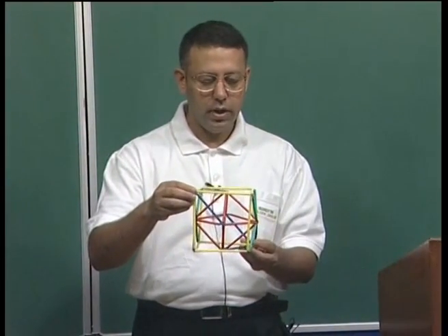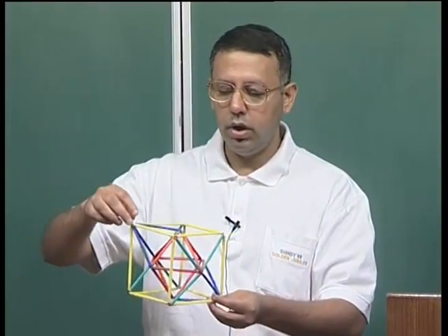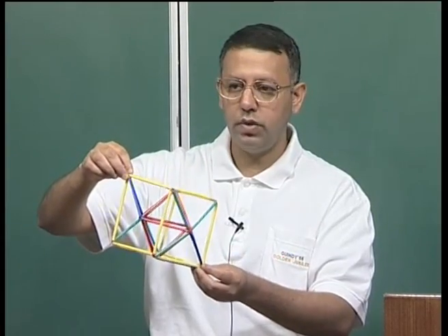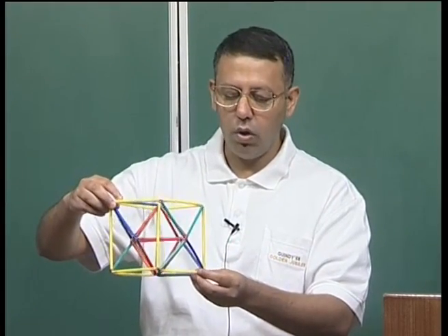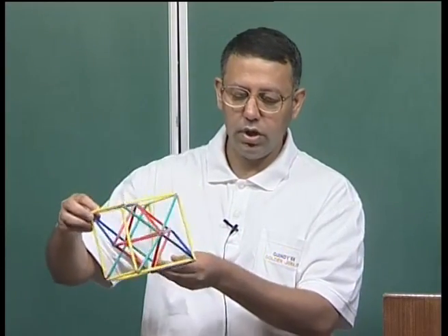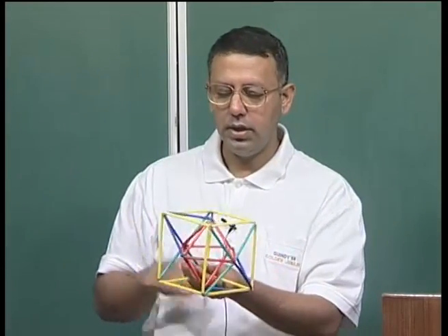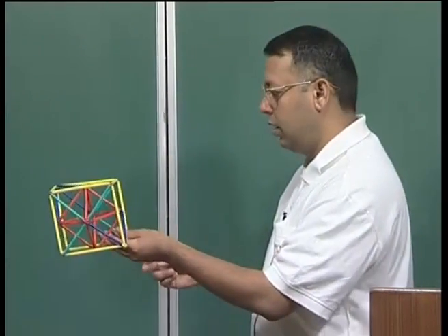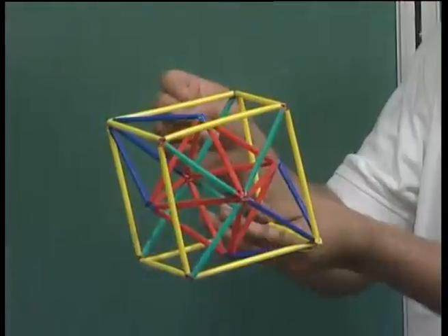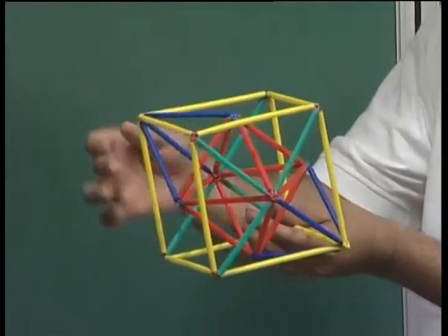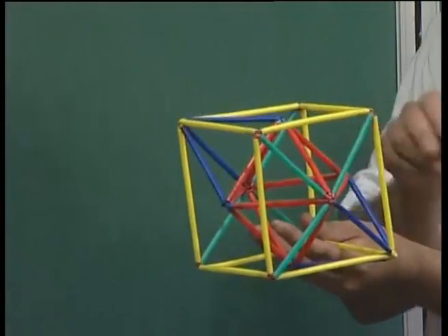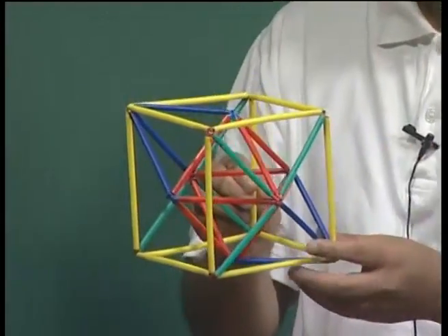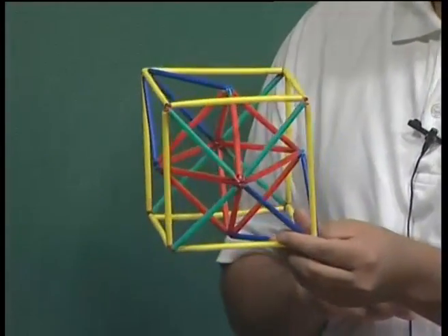As you can see here, the primitive unit cell is oriented along the 1 1 1 direction of the cube, and the 1 1 1 direction is the direction along which the centers of the tetrahedron, which is now in blue and red outlines, and the other tetrahedron, which is also in blue and red outlines, lie. Let me rotate myself a little bit. So in the green background you can see this is my blue outline, this is my red outline. So this is my tetrahedron, and then you have the central octahedron which consists of 8 faces and which is centered at the 0 0 0 position.